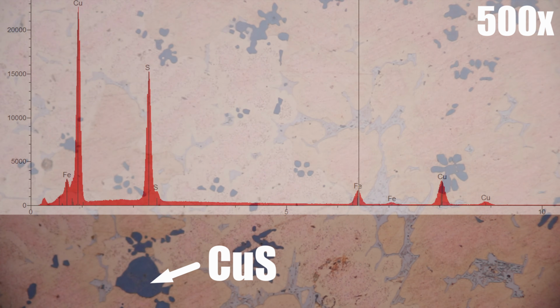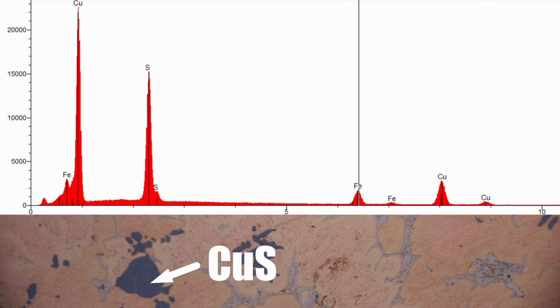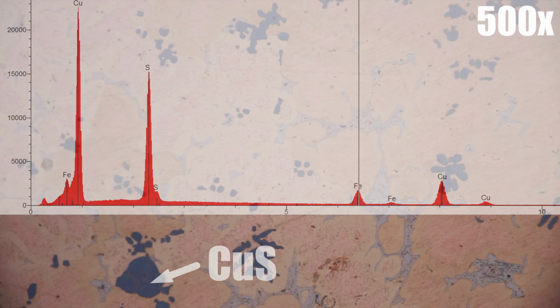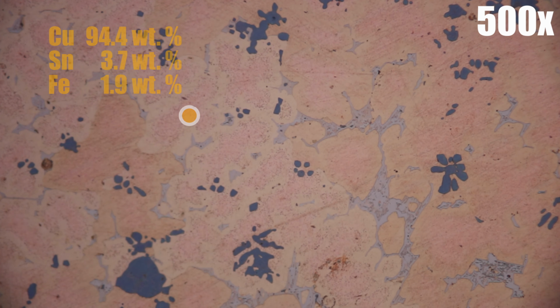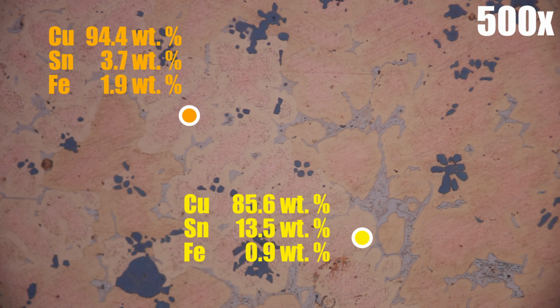By the way, I checked the dark colored phase and it is indeed copper sulfide. The rest is, of course, copper tin based material with some iron. First of all, the grains are heavily cored. The cores contain 3.7% of tin, while the rims have around 13%. And between the copper grains is a tin-rich so-called delta phase, known for its light blue color.